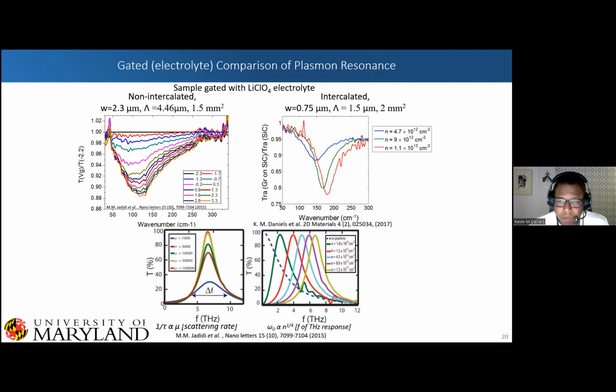And so one of the other things we wanted to show was not just the width, but actually gating. Can we shift our plasmon resonance through gating? And so this is a non-intercalated sample here to the left. As you can see, the resonances are pretty wide, mainly because of the lowered carrier mobility, as well as the scattering associated with it being coupled to the silicon carbide. But in our intercalated case, as you can see, we get really narrow plasmon resonances.